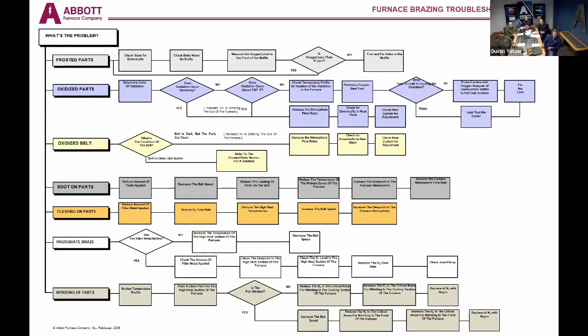So anybody on the call that's brazing and potentially even sinter brazing, you see where you have your pocket with your braze pellet, your preform or a liquid type paste, and you get flashing where it actually wets across the surface rather than staying in the braze joint. So sometimes that's the amount of filler metal, especially if you're applying paste. Sometimes in a manual application of paste, it gets a little excessive. Sometimes it's a simple reduction of hydrogen flow, and increase with a backup of nitrogen or argon, depending on your part. So if we have too much hydrogen, we clean that surface too well, that paste will tend to want to flow across the part rather than down into the joint.